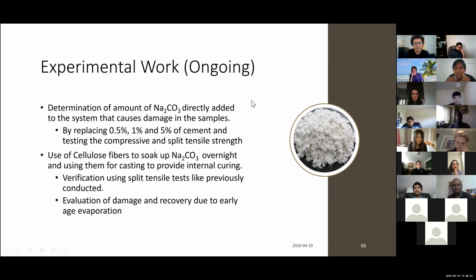In terms of experimental work that I was doing and which was stopped due to the lockdown, Obina was helping me figure out these testings. We were trying to determine the amount of sodium carbonate that can be directly added to the system, and see which amount actually causes damage inside the system. We first tried replacing 0.5% and 1%. We have done these castings already, and 5% we have not done, but these can later be compared with control concrete to see what the impact of each percentage of sodium carbonate is.